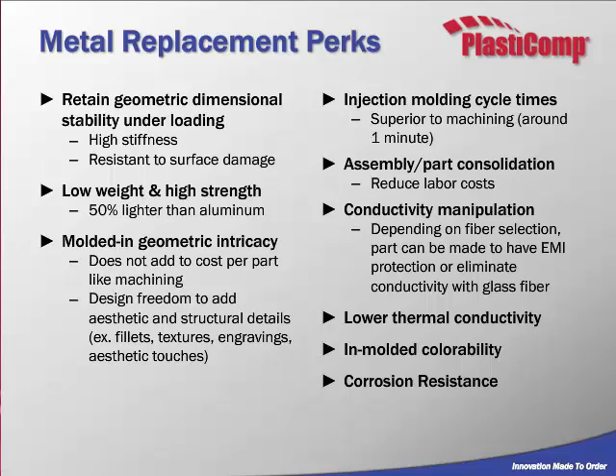Okay, so another few attributes that are nice when it comes to metal replacement is that this retains geometric dimensional stability under loading. More easily said, it's quite stiff, especially when you're dealing with carbon fiber. Glass fiber is also much stiffer than virgin resin also. And the fiber also helps to resist against surface damage, and that's because the fibers are going right up to the surface. So when you scrape the part, you're still having fibers holding whatever details as in texturing on the surface.